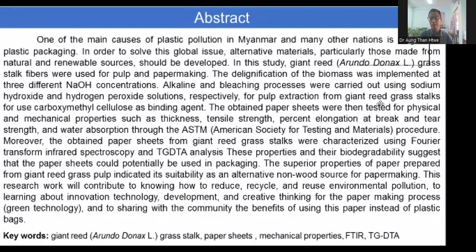The delignification of the biomass was implemented at three different sodium hydroxide concentrations. Alkaline and bleaching processes were carried out using sodium hydroxide and hydrogen peroxide solution, respectively, for fiber extraction from giant reed grass stalk, using carboxymethyl cellulose as the binding agent. The obtained paper sheets were then tested for physical and mechanical properties such as thickness, tensile strength, percent elongation, tear strength, and water absorption through the ASTM methods.